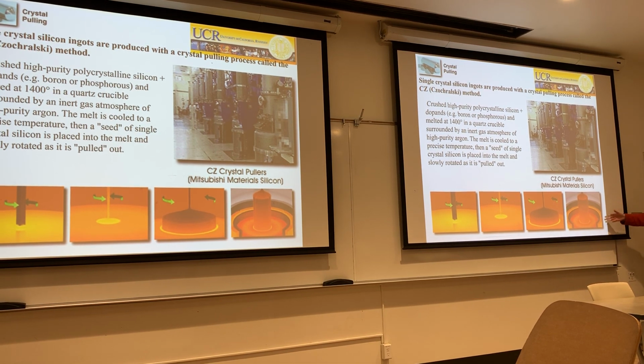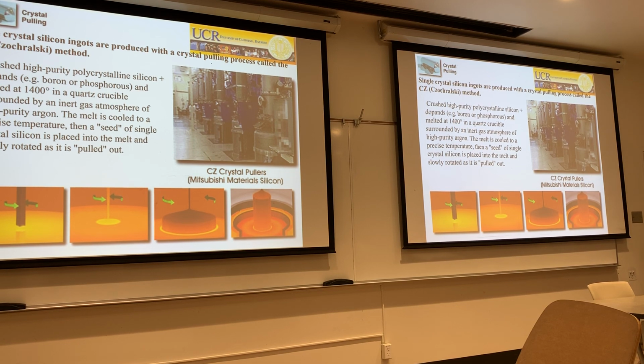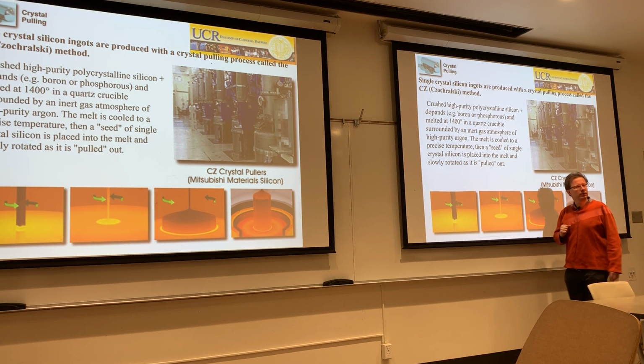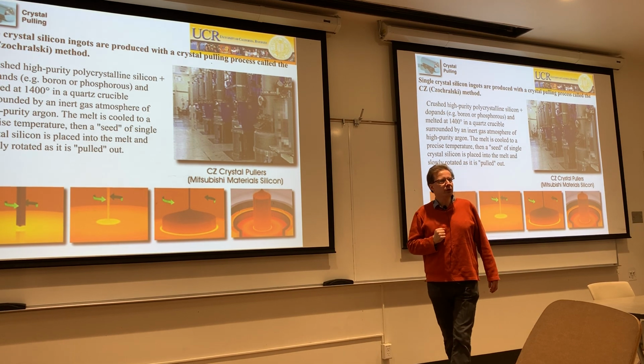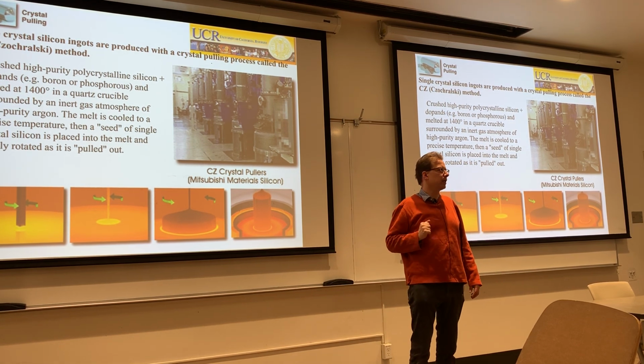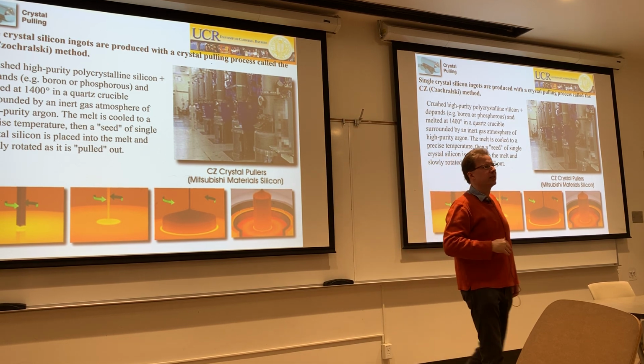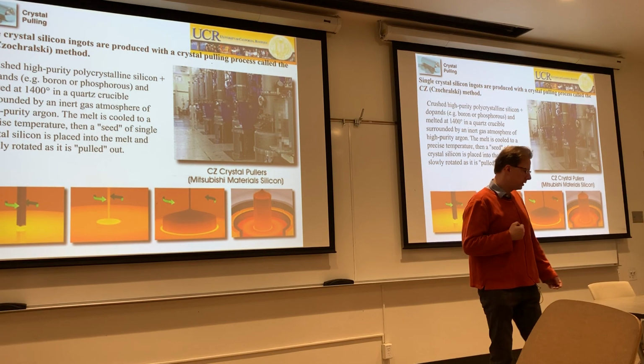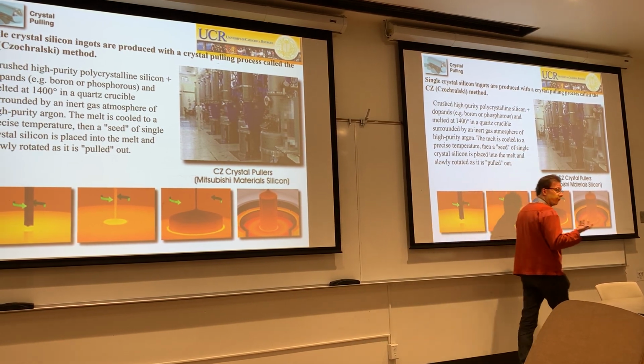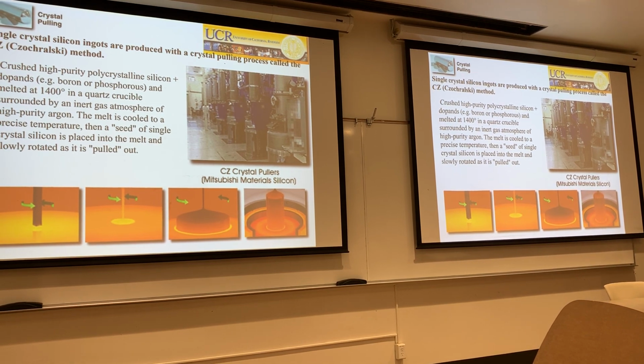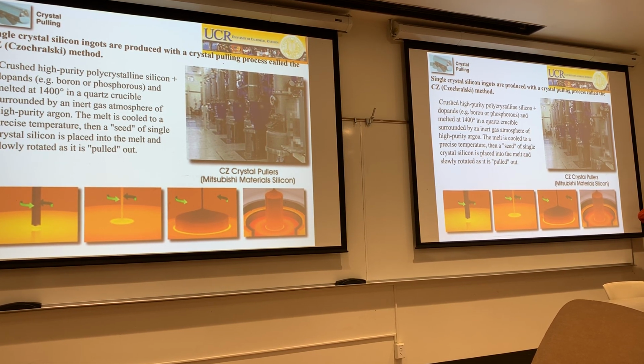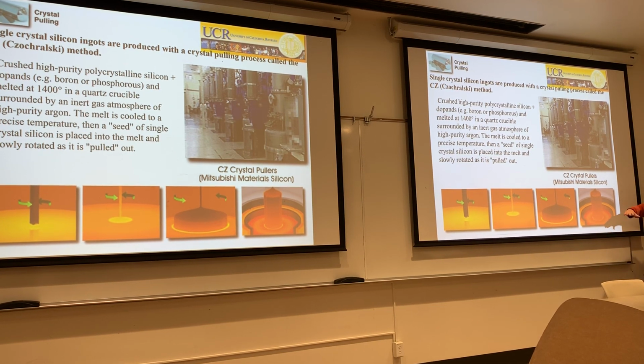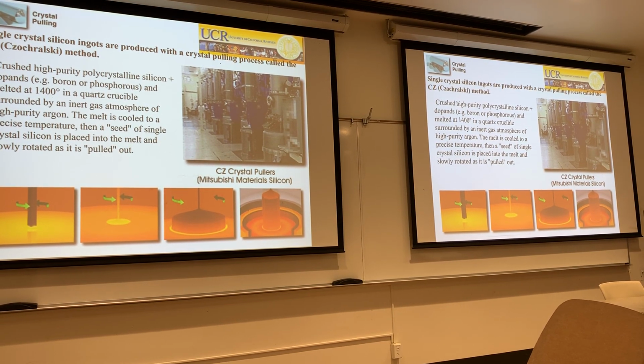Next job, and of course there's lots of chemistry involved in making these melts. The next job would be to dice this thing into wafers. The unfortunate thing is that if you use a normal saw to just dice it, you're losing about half the material, just because the saw blade is so thick, and you can't otherwise make it so thin. So there are efforts in the chemistry of dicing, of cutting, in making thinner cuts with wires, partially electrochemically biasing wires, setting up the right system so that you get very fine wires cutting through the ingot over time in a chemically reactive slurry.